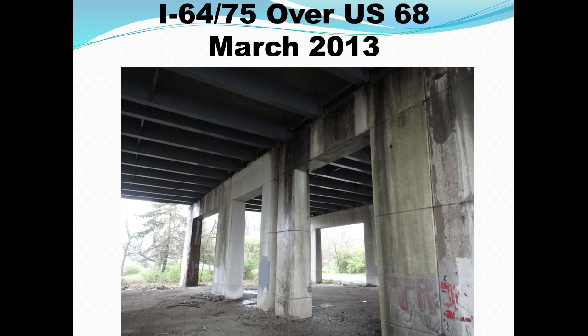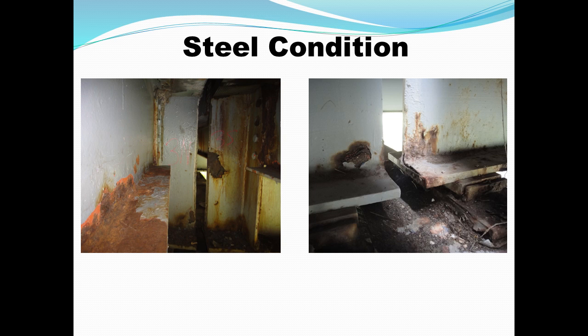And as a matter of fact, just outside of the frame on this photograph, it's much easier to see. You can't see it here probably, but there's spalling concrete and reinforcing steel exposed here, and it's just pretty ugly for this pier cap. The steel underneath, alongside this joint, we have the diaphragms that run parallel with the joint, and this is where we chose to put on the beam ends and on these diaphragms, in some cases, our beam end treatments. As you can see on the right side, the seal is gone completely here. This is sunlight shining through from the deck, and you can also see all the debris and stuff that has accumulated down here, and it was worse in a lot of cases.